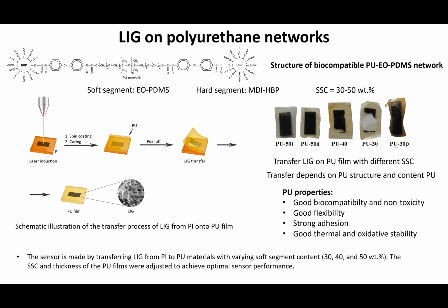In the middle is shown a fabrication procedure. It's a little bit more involved, where here we induce the LIG on a Kapton tape, and then we transfer onto the polyurethane by spinning polyurethane on top and then peeling off the LIG from the Kapton to the polyurethane. We have two different ways of doing this. And then depending on the soft segment content, you actually get different transfer quality.